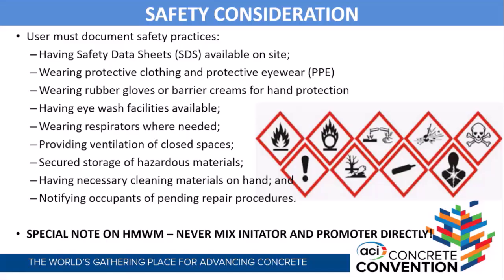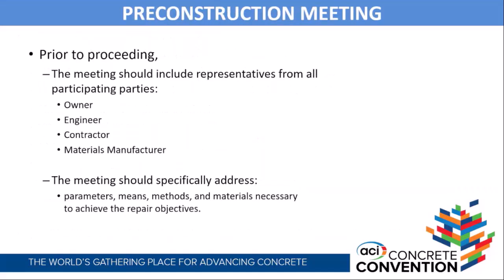There's a special note that the document provides for when you're using high molecular weight methacrylates. Typically, there are three component materials. You have a monomer or a base resin, you have a promoter, and then an initiator. And you can't just mix them all together. You have to make sure that the initiator and the promoter are not mixed together. You'll end up with a violent combustible reaction. And that's not something that anybody wants on their project. So what you have to do is pre-dilute the promoter with the monomer or the base resin. And then after that, you can add the initiator to the rest of the material. So all of that has to be kept straight.